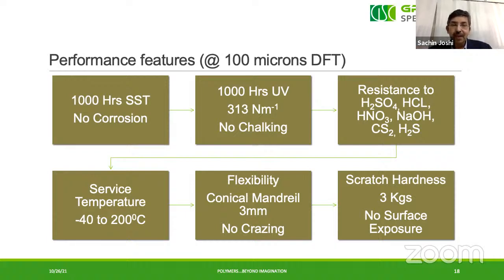Now if thickness is a parameter of performance, then you can take a wax and put a 4 mm wax. Will it perform? No, because wax doesn't have properties to perform as a protective coating. So what is important is the properties of the polymer coating going on the surface. And since this polymer molecule has very high performance properties, thickness is not important in this case. So we have tested all the properties on just 100 microns of dry film thickness.